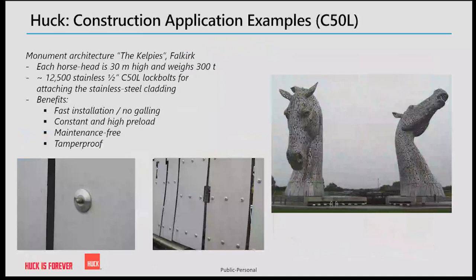And here the customer wanted a fast installation without any issues in regard to galling. For example, if you want to install a threaded fastener, you always have to use some kind of lubrication. Otherwise, the nut and the bolt will gall, and it's not possible to apply a defined preload. Also, the preload scatter is an issue because the structure is exposed to high winds and a lot of wind loads. So it's a dynamic structure, and since there were more than 12,500 fasteners used, it was impossible to maintain the joints, to retighten the joints, and check for preload. So that was also a reason to choose a Lockbolt. And also, since this was made of stainless steel, it should be tamper-proof to avoid any tampering.